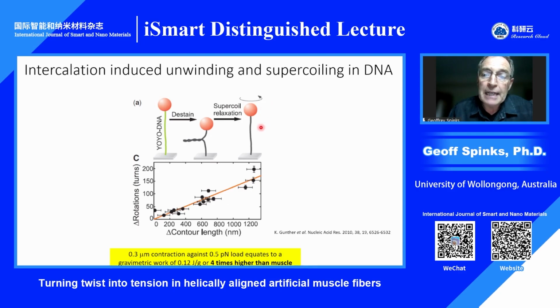Just like is happening here on the right with a single strand of DNA. Now, the data published in this paper, I was able to analyze, and the interesting thing is that the work done during the contraction of this particular example here comes out to be about 0.12 joules per gram, or 4 times higher than muscle. So DNA supercoiling could be used as quite a powerful molecular motor.